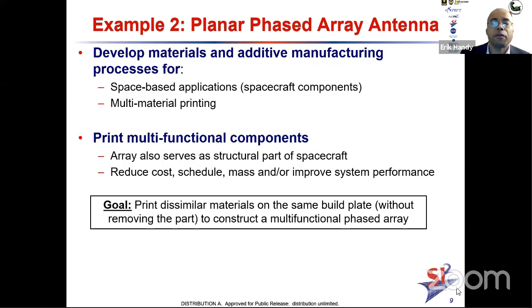This is a planar phased array antenna. As I'll show you in a slide or two, we also looked at a 4x4 array here. Now the challenge here was we had some funding from the Air Force to look at space-based applications. And so we needed to be 3D printing parts with space compatible materials. And we also needed to be co-printing dissimilar materials, as I discussed in a slide or two ago. So thermoplastics and conductors, we didn't have the benefit of a plating process. So we needed to be able to co-print different materials that make different demands on the printing and have different post-processing requirements.